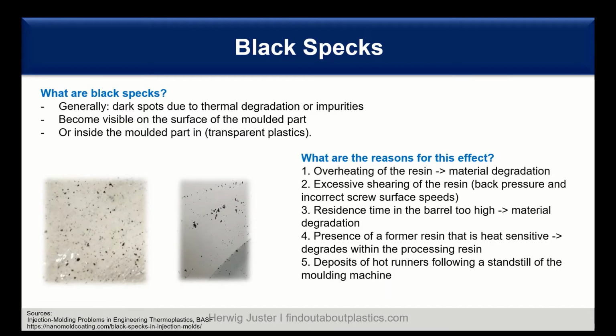And what are now the reasons for this effect? So the first thing is overheating of the resin. So this results then in material degradation and the black specks. It can also happen that you over-shear the material, resulting also in material degradation, due to high back pressures and incorrect screw surface speeds. Then another factor is the residence time in the barrel itself, and also in the hot runner system if you have one. This also leads to material degradation and black specks.